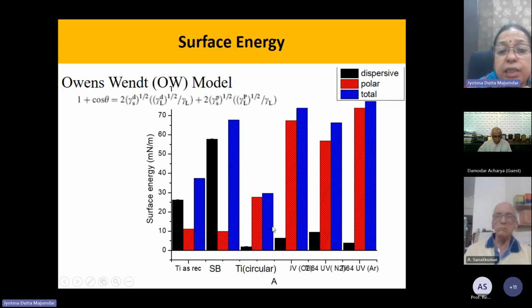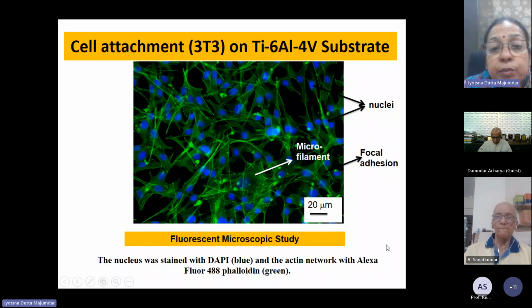This is also important because surface energy is minimized here, though it's comparable to the as-received sample. We also saw that wettability is much lowered here, because it's not wettable at all. So it's offering good corrosion resistance. But from the cell attachment point of view, wettability is also very important. The higher the wettability, the higher the cell attachment.